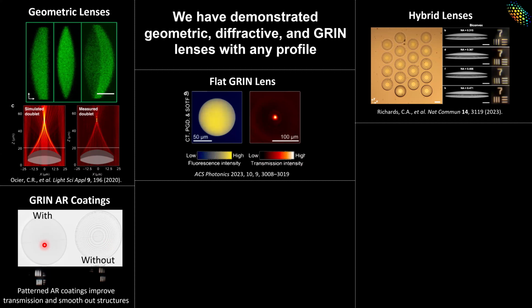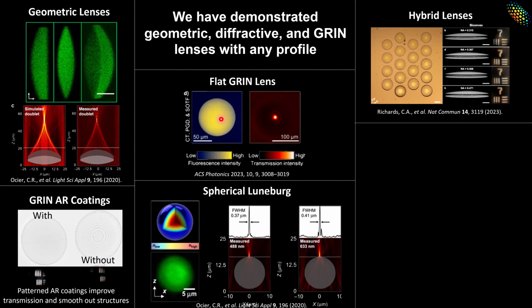But then, we can also just make fully GRIN lenses where geometrically, this is just a flat puck of material that has a higher index on the inside and a lower index on the outside. And that can be essentially any profile. In this case, it's a linear profile. So this functions as a GRIN axicon. But then we can make fully 3D gradient index structures.